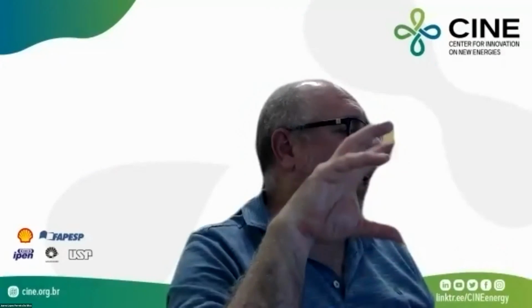If you look at the relativistic effect on the lead, I would say that it has a point, because the relativistic effect makes the inner states shrink, and then the s state is going to expand. It'll be more delocalized. This will play some role. Now, when you talk about tin, the facility with which tin changes the state from 4 to 2 is much easier. And these octahedral distortions can even make this easier, because if you change the state, you go from a coordination of 6 to a coordination of 5. If you have a lot of distortions, tin will tend to change the state. That's true. But in that case, it's not the relativistic effect, but the structure problem that might be the cause.